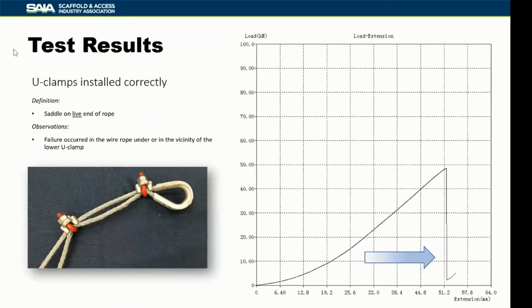As I said, we wanted to look at U-clamps and see how U-clamps actually perform. If you look at this with 2 U-clamps properly installed, they actually don't perform much worse than some of the other techniques. The breaking force was around the same, close to the 11,000 mark, and the failure occurred in the vicinity of the lower U-clamp.